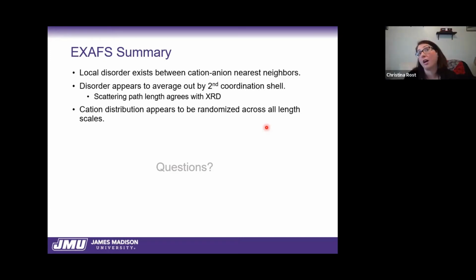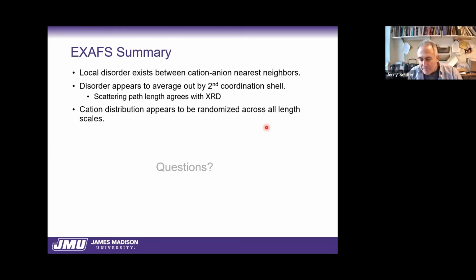It is not a knob I can easily tune for the rock salt structure. I know that other people have done it with perovskites and a couple other phases, but I can't speak to that very much. I see. When we try to change the oxygen deficiency, if we reduce the sample, it phase separates. If we over-oxidize the sample, it phase separates. I see. Interesting. Okay.